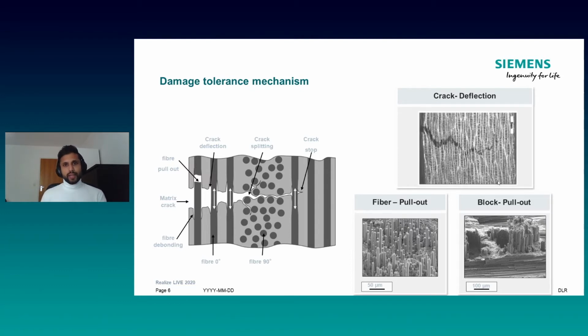This crack deflection can happen at an individual fiber, as we see in the case of fiber pullout, or the crack can go along the fiber bundle, as we see in the block pullout.